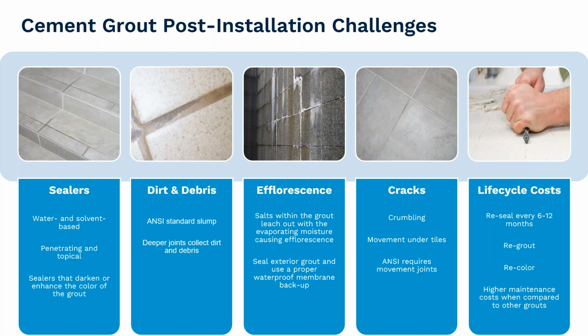So we do have some post-installation challenges. You now have the grout up and it is cured. These are some of the challenges you're going to see as you go through and the grout is cured and you go back to revisit the job. You do need some sealers. Those sealers should be water and solvent based. They're penetrating and topical, and the sealers can darken or enhance the color of the grout. So if you do put a sealer on, it could cause the color to be a little bit darker.